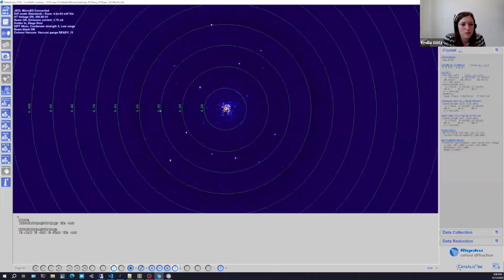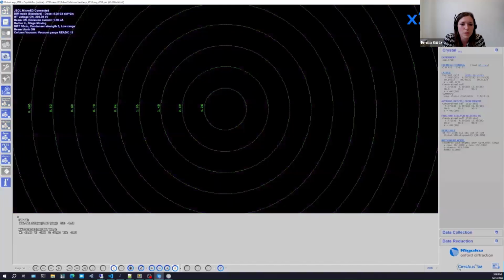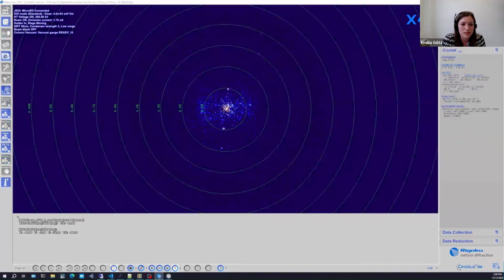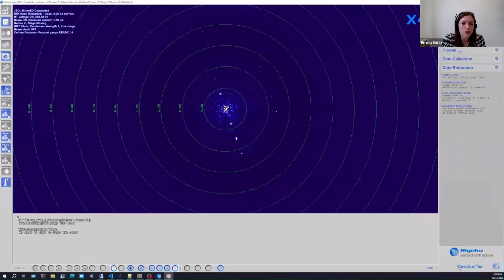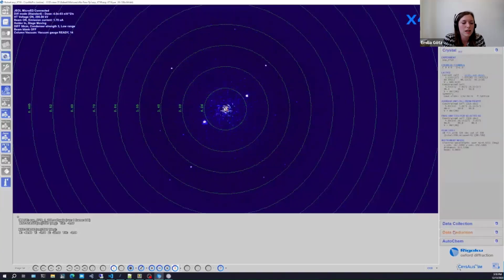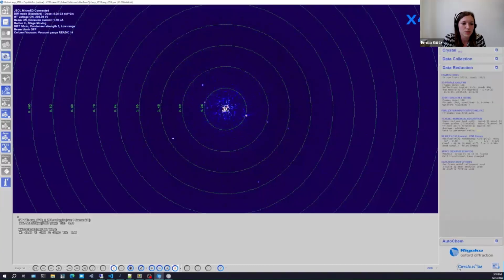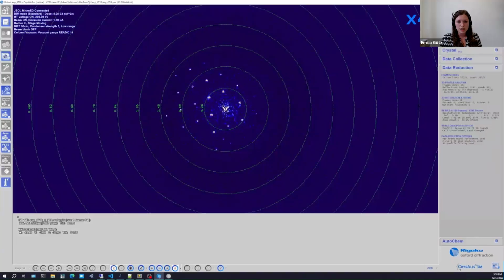So once we click on Start Experiment, the stage will move to the starting position, which is minus 65 degrees in this case, and then it will start the diffraction experiment. And concurrent to the data collection, we can see on the right-hand side that the data is being processed by CrysAlisPro. So first it will look for a unit cell, and when it has determined the unit cell, data will be integrated and reduced, and then after enough collected data, AutoChem will start.